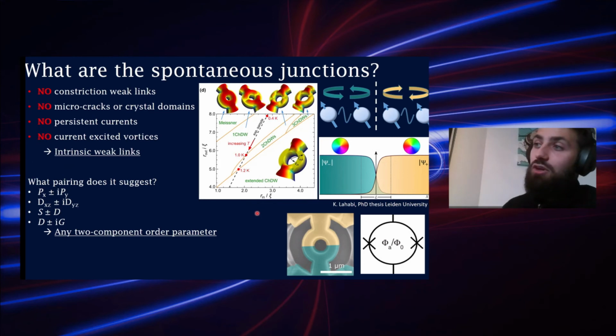Each choice of inner and outer radius gives you a line through this phase diagram that is temperature dependent. Once you go to higher temperatures, the coherence length increases and then blows up at Tc, so you move towards the lower left of this line, and for lower temperatures you move to the upper right. For example, at higher temperatures there might be two chiral domains, and at lower temperatures there might be one.